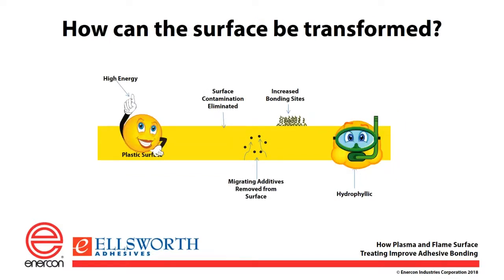If you go to the next slide, a hydrophilic surface has high surface energy. You generally remove the surface contamination so that you're not bonding to the contamination, you're bonding to the material itself. You've either removed or you've done something to affect the migrating additives, and that's increasing your bond sites and giving you a much higher surface energy and a better bond.